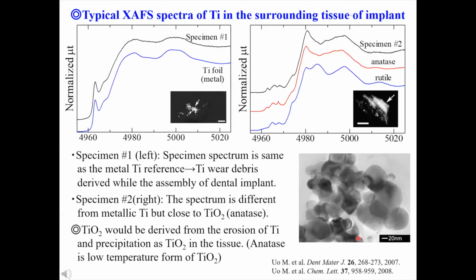This slide shows the absorption spectra of two different types of titanium-accumulated mucosal specimens. The black line is the spectrum of the specimen, and the blue and red lines are the standard specimens of titanium metal and oxide. In the left figure, titanium in tissues shows a spectrum similar to that of titanium metal. Therefore, the accumulated titanium in this tissue would be metallic titanium debris, which might be generated by the implant surgery. In contrast, the right spectrum shows a different shape. The spectrum derived from the specimen was similar to that of anatase-type titanium dioxide.